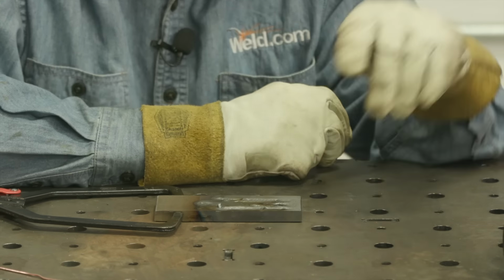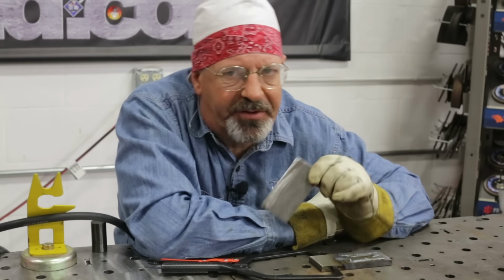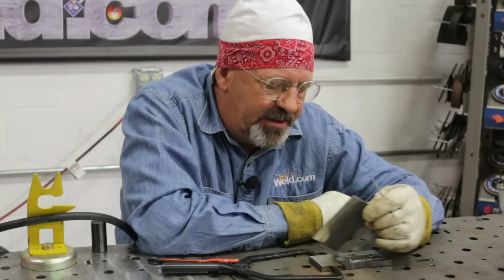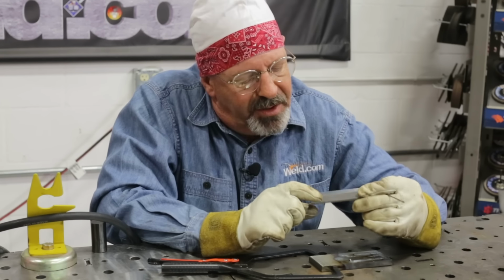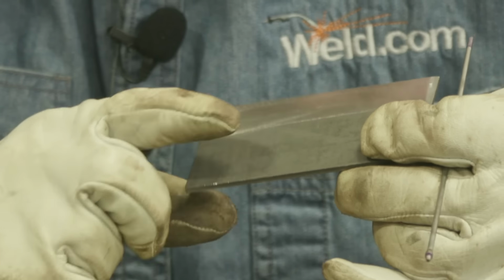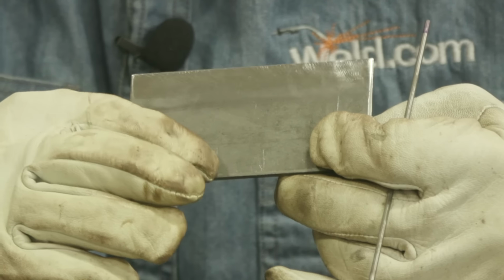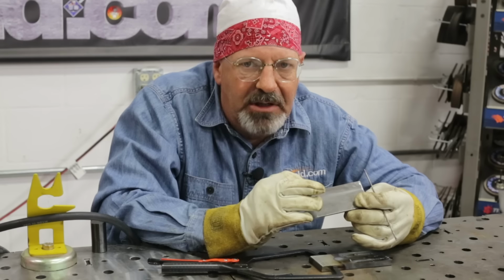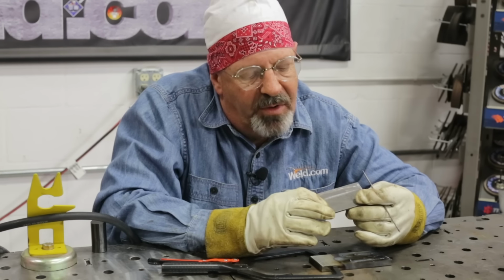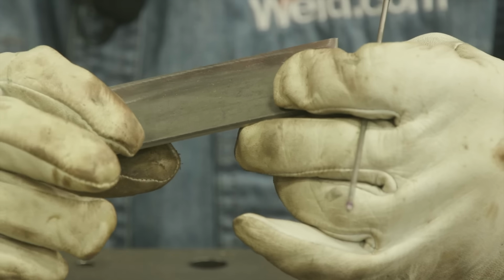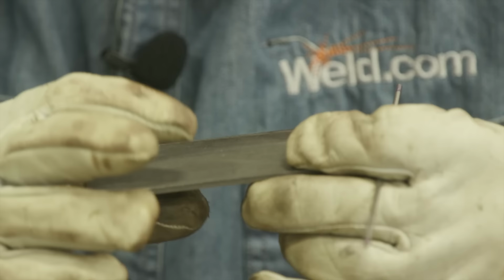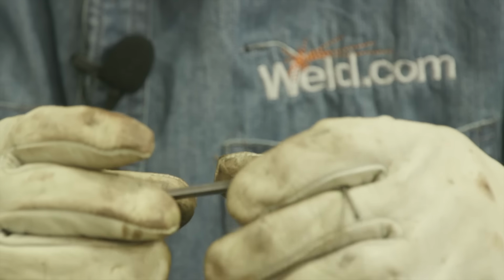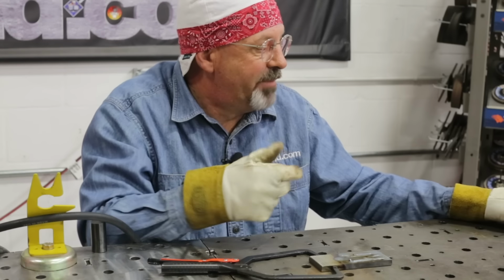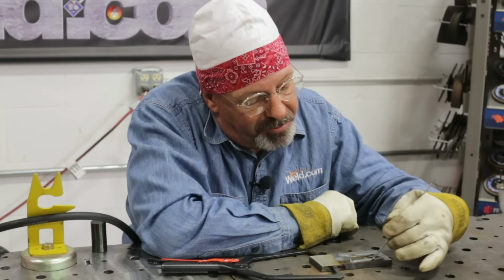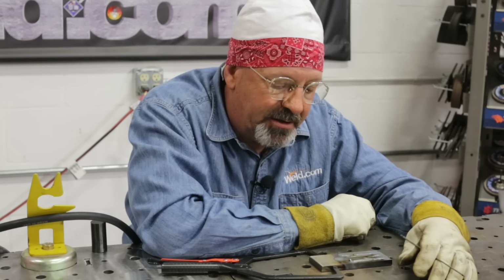One thing that we didn't do was weld on mill scale. All of these plates are cleaned of mill scale. Mill scale is, you may get brand new material. It could have this pickling, but this light gray on here versus this shiny. You need to clean all this off before you weld. Welding over the top of mill scale will produce some discoloration of your beads, and it'll look pretty bad. Could cause some porosity as well. Maybe that's where some of that brown orangey stuff comes from. Been a while since I've been able to produce it. Some of this just looks gray and weird, but I wasn't able to get the nasty colors I'm talking about, and I apologize for that.